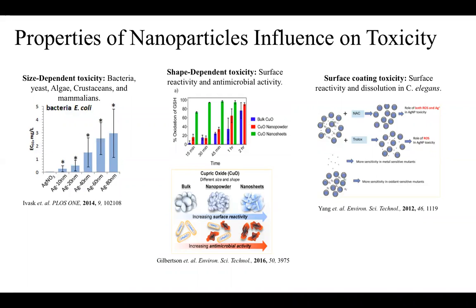For example, Ivask looked at different nanoparticles of silver nanoparticles from 10 nanometers to 80 nanometers and was able to see the difference between how they impacted the growth of bacterial strains. And again, the smaller nanoparticles led to higher toxicity, but at the same time, they were discovered by different rates of how this happens. And opposite of that, Gilbertson was able to look at copper nanopowder sheets versus bulk species to compare how changing that surface growth directly impacts the reactivity or the antimicrobial response of copper as well.